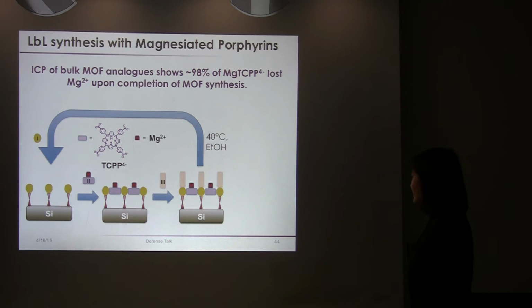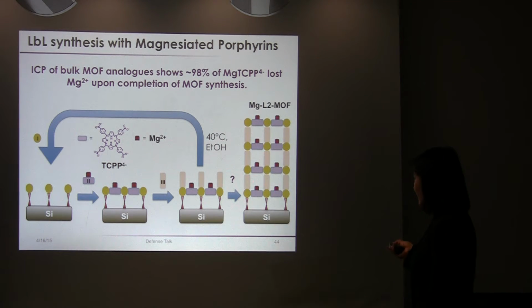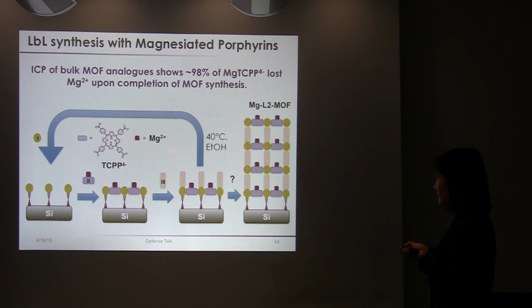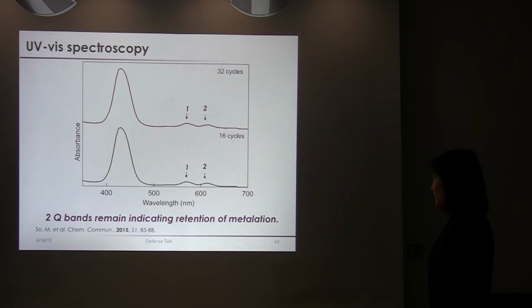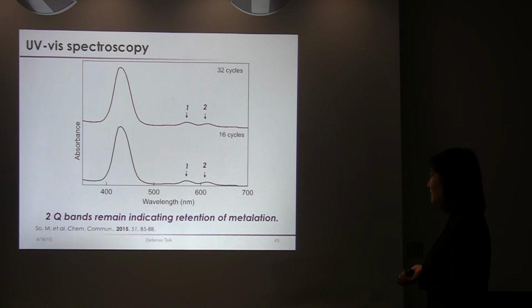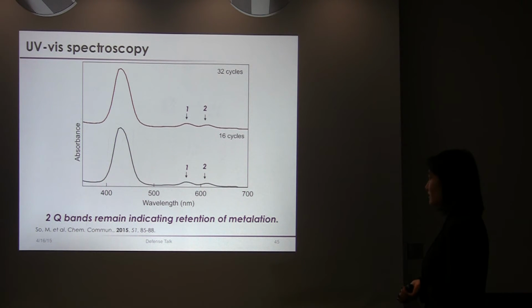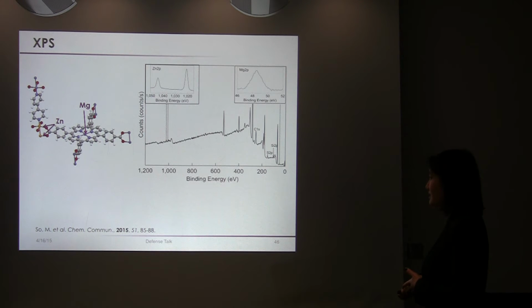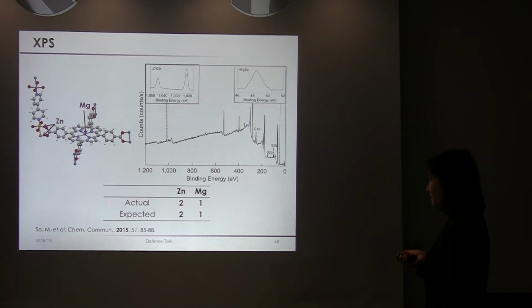Yeah. And so I wondered if I could actually retain the weakly bound magnesium 2+ ions in the porphyrin core after LBL synthesis. So again, I checked UV-vis spectroscopy, and this also indicated that there was retention of the metallation. But to check the metal identity, again, I checked XPS, and I expected, again, a 2-to-1 ratio of zinc to magnesium, and indeed that is what I observed in the XPS spectra. So this was also a very promising result.